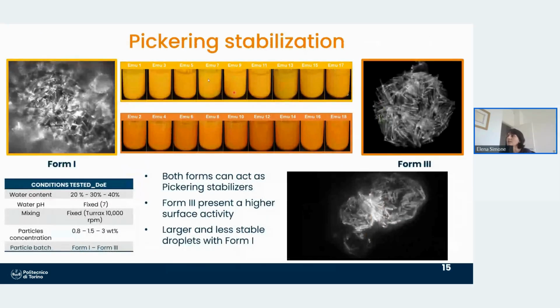And then we prepared these emulsions. So those that you see are water in oil emulsions. What is very nice already is that the two polymorphs have different colors. Form 1 is yellow, form 3 is orange. So even from the point of view of using natural colorants, we can use different polymorphs. This can be quite useful.